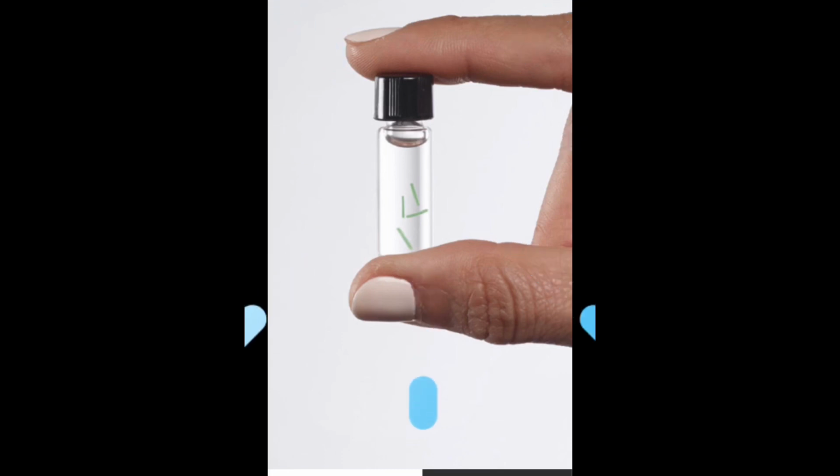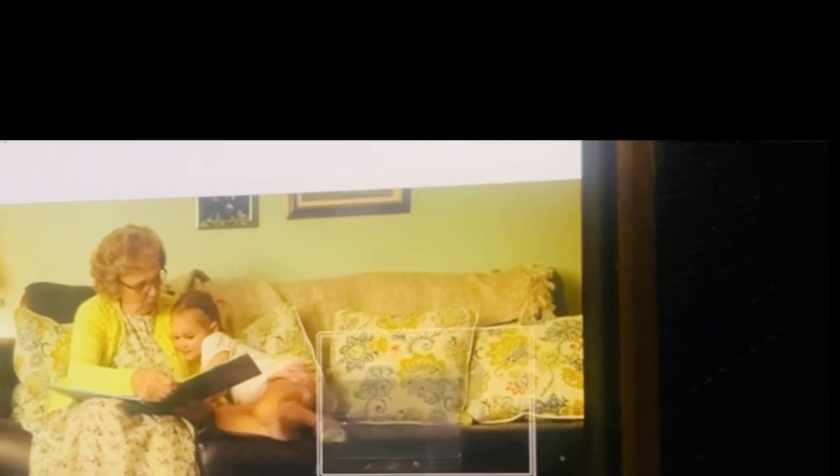It mimics the scaffolding that the body naturally would produce to allow cells to grow, which makes the heart the shape of the heart, a kidney the shape of a kidney, or the liver the shape of a liver. That's done through this scaffold called the extracellular matrix. Our sensor basically mimics that extracellular matrix, so the body doesn't see it as foreign, and it drives healthy tissue throughout the interior of that hydrogel. We place that sensor 2 to 8, 10 millimeters under the skin, measuring interstitial fluid.